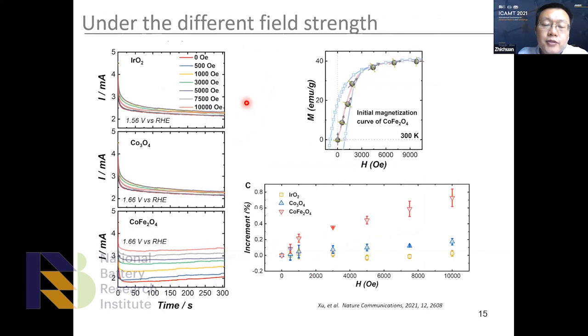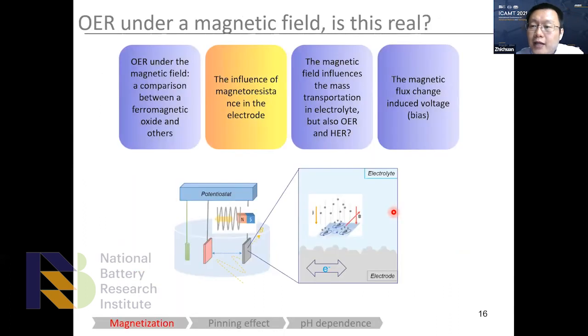And even more interesting, we can find a kind of correlation between the magnetic field strength and the increment of OER activity over here. So all of this is what we observed as an increment under the magnetic field. And now we have to exclude other possibilities to ensure that it really comes from the magnetic field, all right?